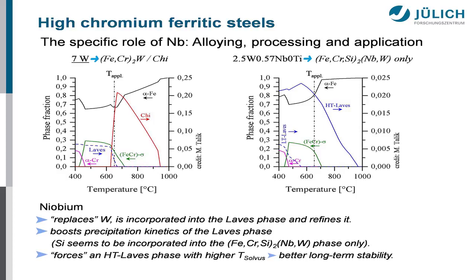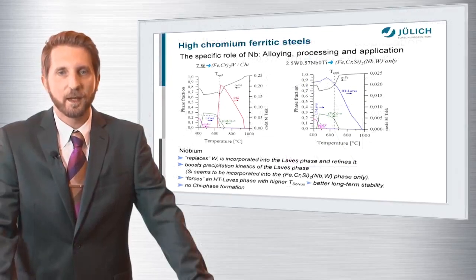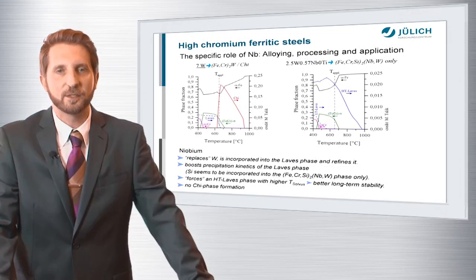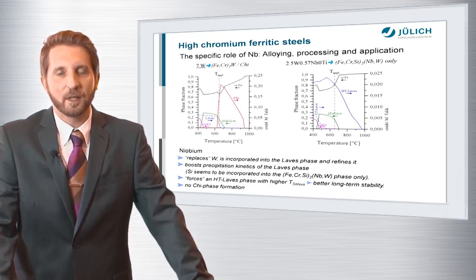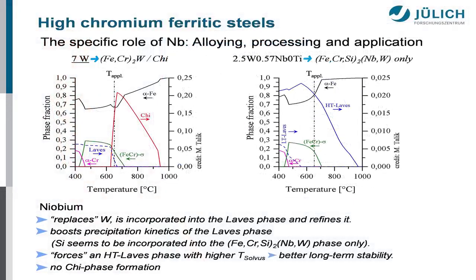It is represented by the blue curve. The dissolution temperature is somewhere close to 970 degrees C. In comparison to the Laves phase in the 7 tungsten alloy, which dissolves at approximately 670 degrees C, the Laves phase in the combined alloying material should have much better long-term stability. And what is beneficial too, if you go for niobium alloying, you do not form the Chi phase. You can see the Chi phase is represented by the red curve on the left-hand side, and you see that in the application temperature range of approximately 600 to 650 degrees C, you do have a very steep phase change from the Laves phase to the Chi phase. And this is what you really don't want to have if you think about cyclic application, where you do have temperature fluctuations quite frequently.